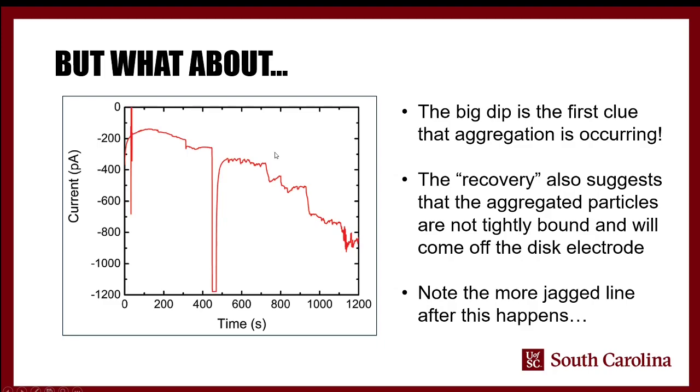And so what we can take away from this is that after this aggregation happens, there's all these particles in solution. They're not actually in contact with the disc electrode, but they're very close to it. And although the general trend is that they hit and stick, there's at least a few cases you can see here where there's a step, but then there's a step back. And so that suggests that these particles are hitting and falling off, and hitting and falling off.